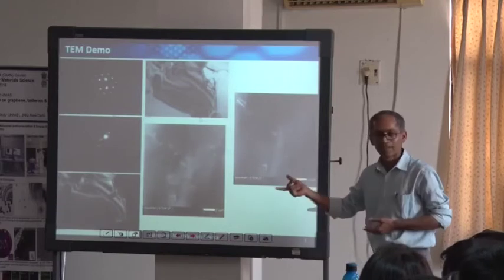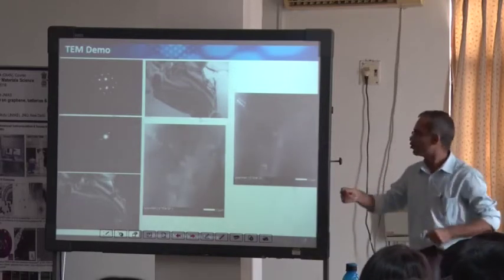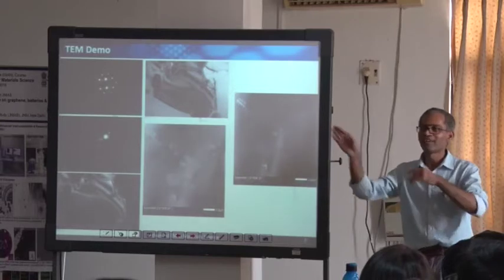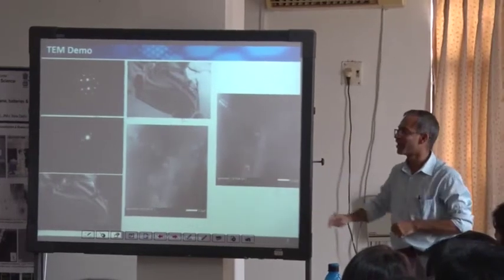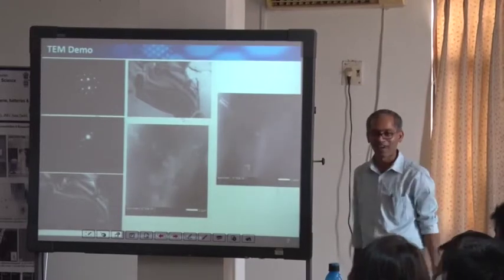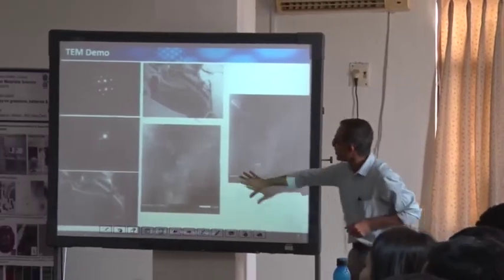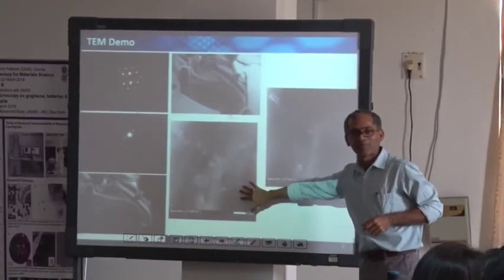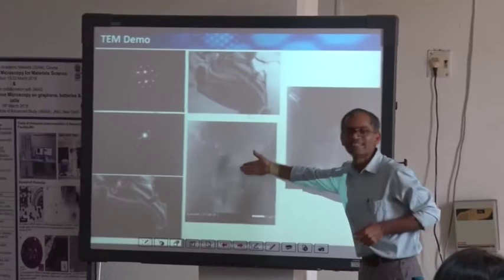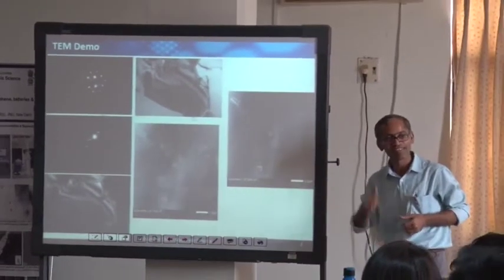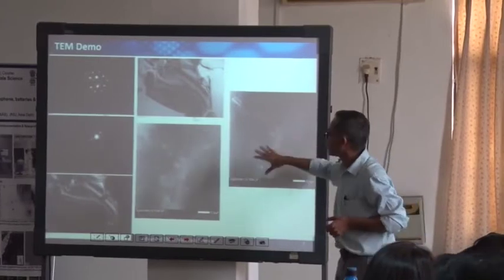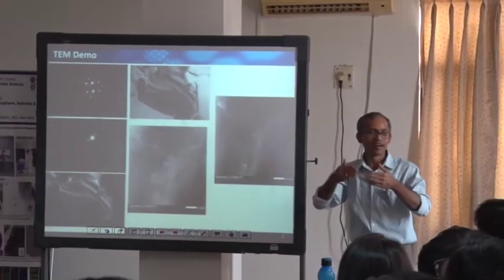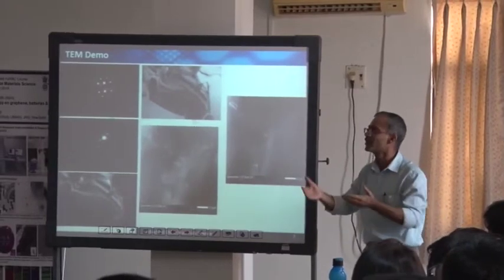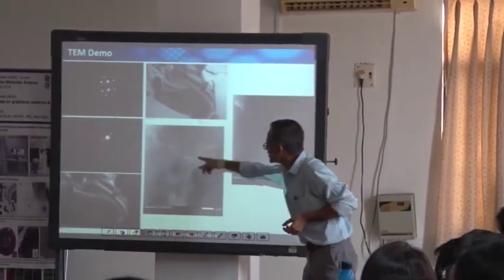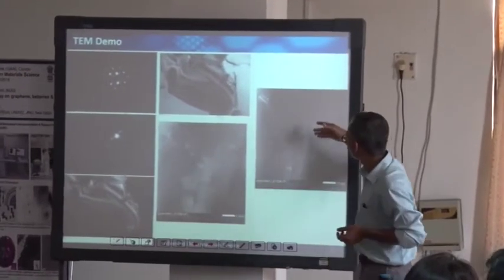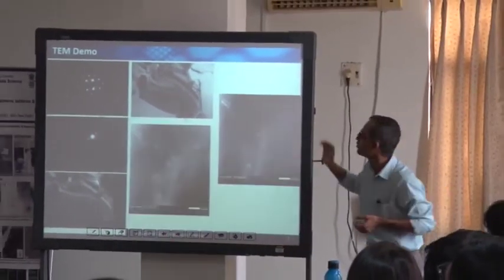And then Professor Benjamin, for whom doing scanning transmission electron microscopy is such that even if you wake him up in the night and ask him to get an image, he will give it to you in 5 minutes. This is a scanning transmission electron microscopy image. You can see again the grains, and you can see the chemical contrast like that of the backscattered electrons in the SEM. And this is the corresponding STEM image, but at a smaller camera length, so that you get the Z contrast. Here there is still some diffraction contrast. You see the grains here; those go away, and only the pure chemical contrast remains, and so on.